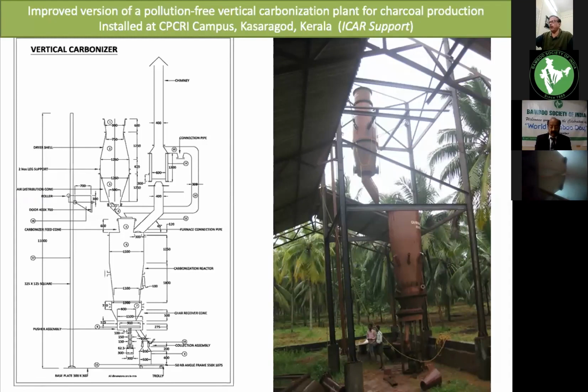An upscaled version was installed at the Central Plantation Crops Research Institute at Kasaragod, Kerala, with support from ICAR. This plant is a little bigger than the earlier one. It is also a carbonizing plant, but a pre-dryer is fitted at the top, so that if the moisture content of the material is a little higher in the rainy season, there can be a pre-dryer, and charcoal can be produced employing this vertical continuous carbonizing plant. Here also pollution is not a big problem because it is a continuous process. We have tested the product quality and found that it satisfies the Indian standards for industrial use.